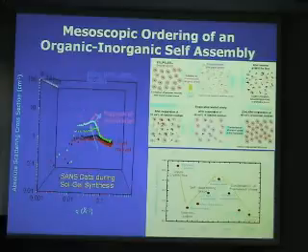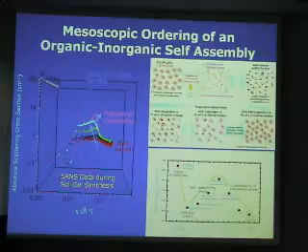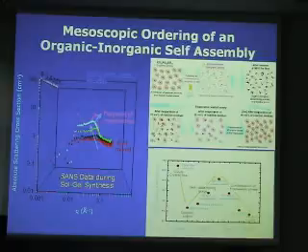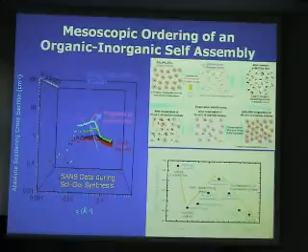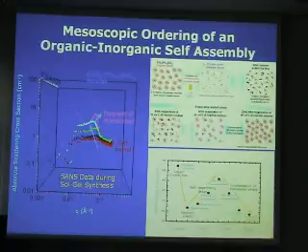Then after completing the packing of the micellar structure, the polycondensation takes place, and then we have a very nice organic-inorganic interconnected self-assembly. Based on this schematic model, we can propose the formation mechanism for this kind of material synthesis. As you can see, we have a very nicely ordered micellar solution at first, in the initial organic phase solution.